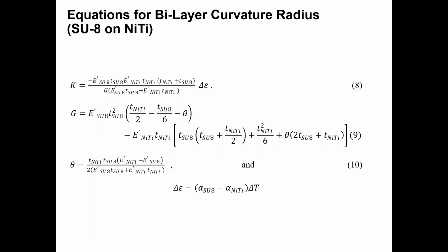So I'm presenting some of the equations used to model and to some extent optimize the curvature and degree of actuation of the SU8 and NiTi film stack. So the curvature term K is described by the biaxial elastic modulus of SU8 and NiTi, which is the E prime terms. And then thickness of the bilayer materials is described by the lowercase t terms. G is also a term involving the biaxial elastic modulus and thickness of the individual bilayer materials. Finally, it introduces this theta term, which accounts for the location of the neutral plane for the various film stacks.